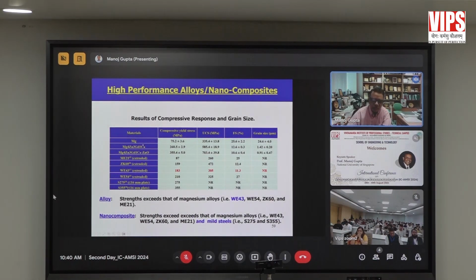For example, if you look at row number 2 here among the elements, you see that this alloy shows a strength of 260 megapascal, UCS of about 585, and failure strain of 12.6%. Now, the importance of this value is that these values are greater than WE43 alloys, which is used in the aerospace application and comes with a very high price tag.